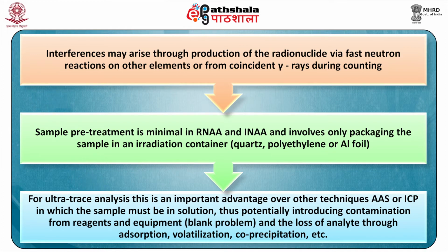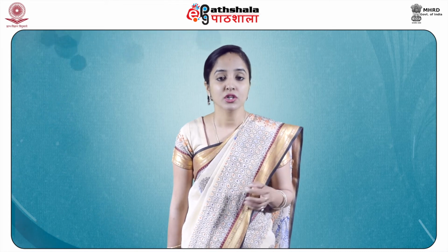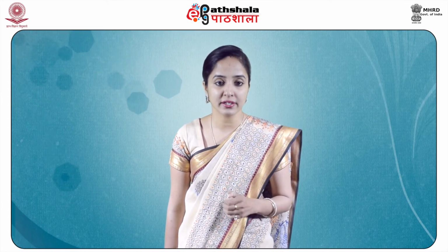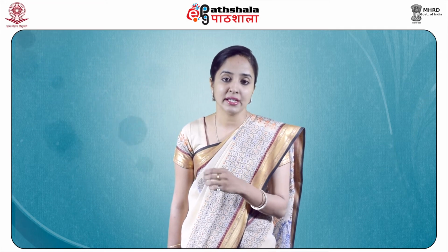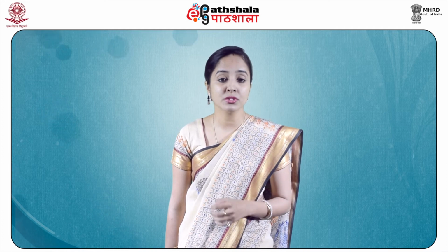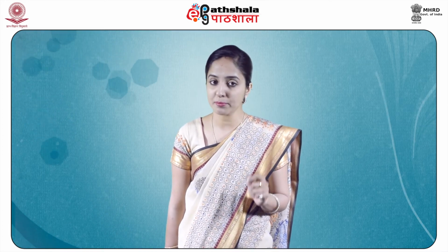For ultra-trace analysis, this is an important advantage over other techniques like atomic absorption spectrometry or ICP, that is inductively coupled plasma technique, in which the sample must be in solution, thus potentially introducing contamination from reagents and equipment, that is a blank problem, and the loss of analyte through adsorption, volatilization, co-precipitation, etc. After irradiation, adding non-radioactive carriers to the radionuclide tagged sample can be done in RNAA techniques, eliminating blank contributions and chemical yield determination of the separation process.